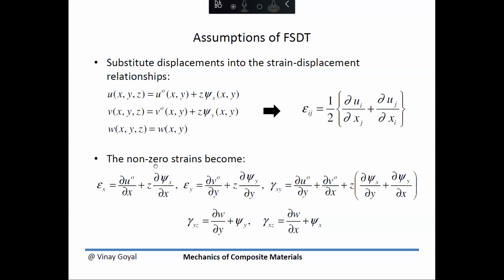So I can take these strains that you see here, and we can put them in a way that's easy to digest. I want you to notice how these in-plane strains are a function of mid-surface quantities, but they're also a function of Z through the thickness, following these gradients of these psi_x and psi_y. Notice how gamma YZ and gamma XZ do not depend on Z, so therefore they're constants. They're constant across the thickness of that composite plate.